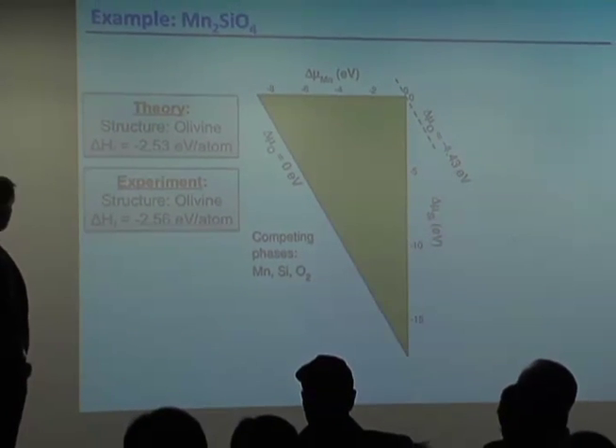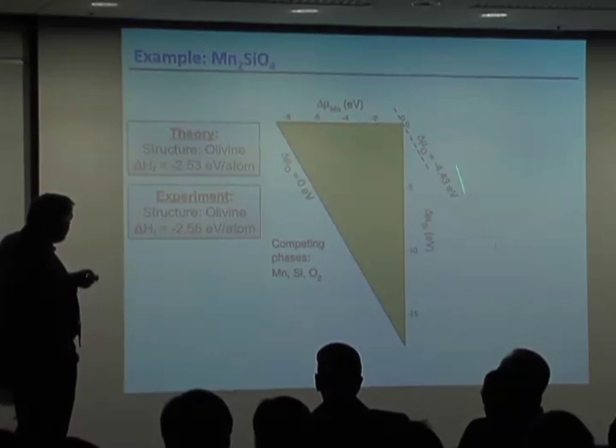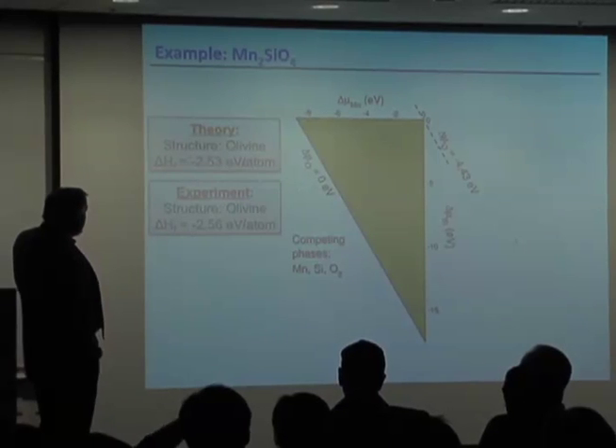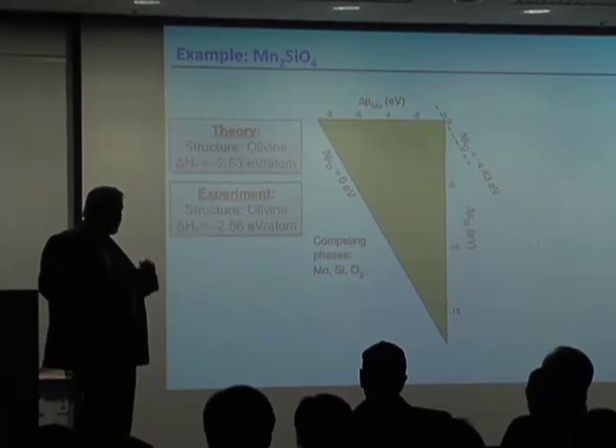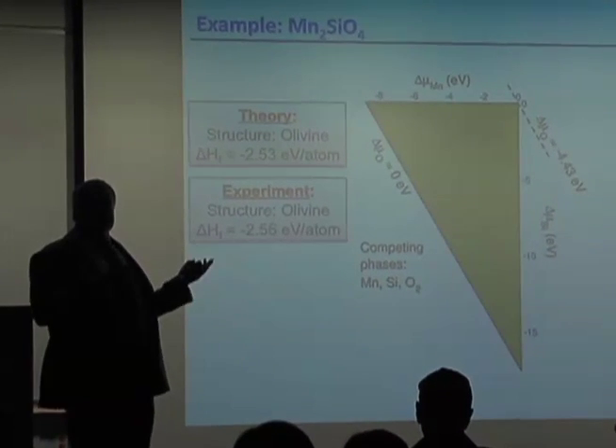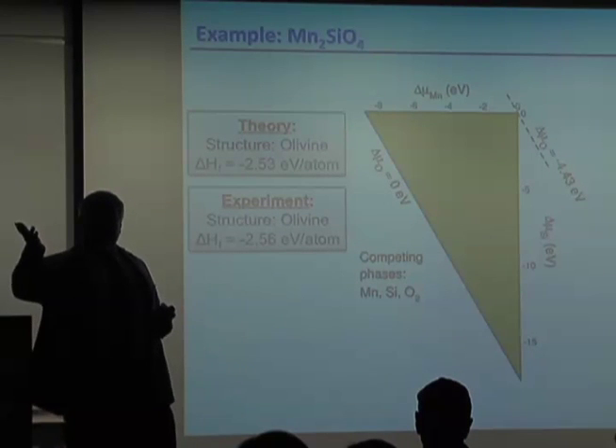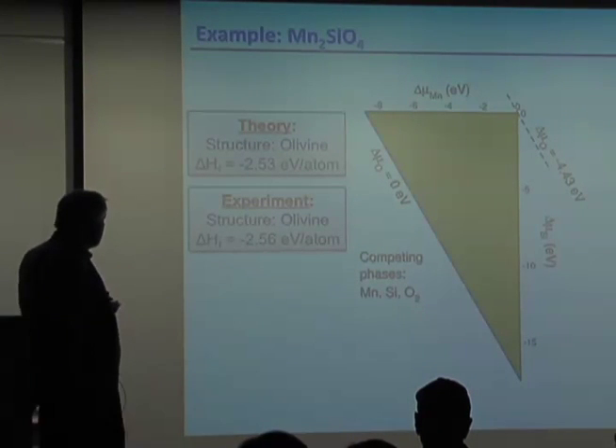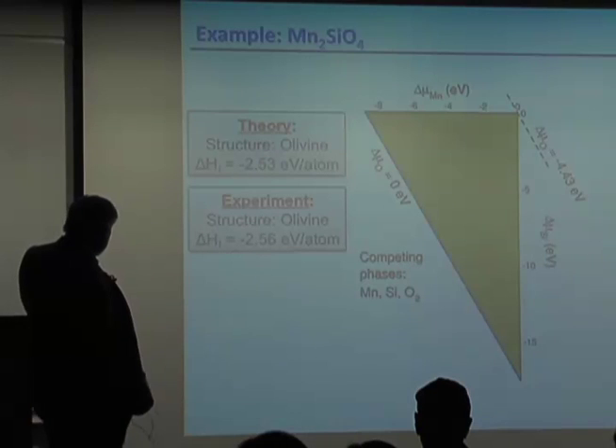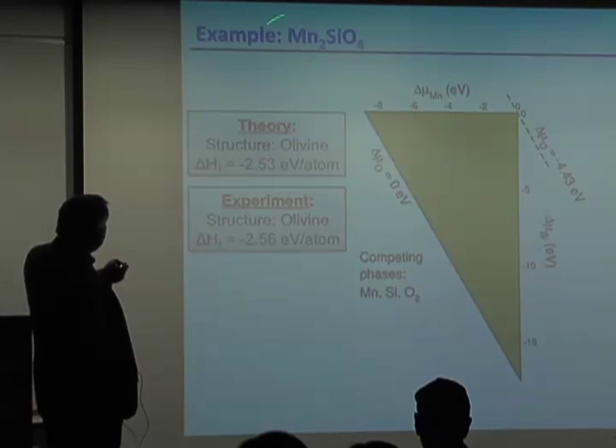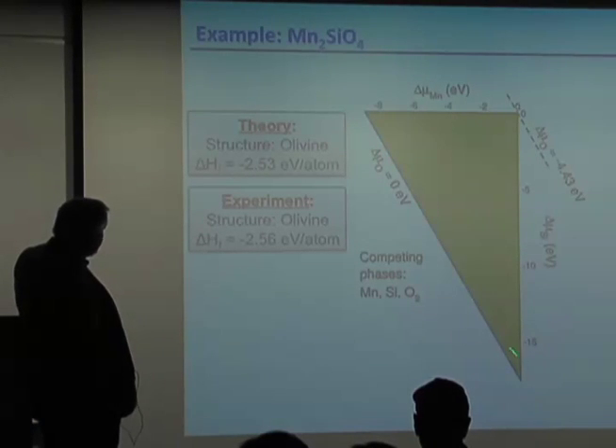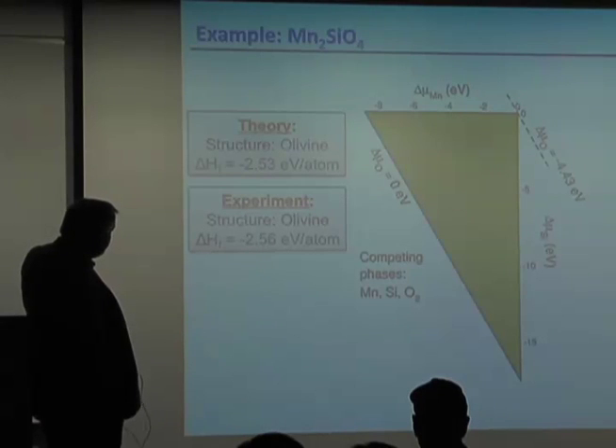The other piece, of course, is to think about the chemical potential for each of these elements and to ask, how would I work in what process space? Because some material might be stable under high oxygen concentration, but not under low oxygen concentration. And so here's an example of how this works. Here's a compound. We predict, if you look at it relative to just the elemental competing phases, it has a negative heat of formation, so it's stable over all these process conditions.